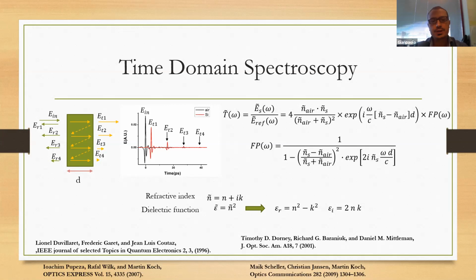The back and forth mechanism of the internal reflection has a clear fingerprint in the time domain signal. Here you can see my pointer. So the black signal is the reference one, that is the intrinsic signal generated by the system in absence of the sample. When we put the sample, we can see the red signal that is composed of the main transmitted signal that is delayed and damped according to the complex refractive index of the sample. And then the multiple reflections can be seen, according to Et2, Et3, Et4, and so on.